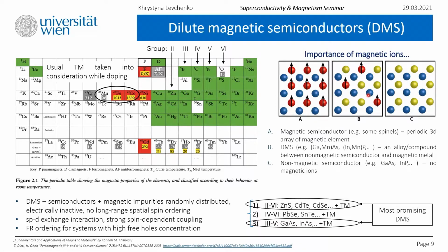The most characteristic feature of the DMS is a giant spin splitting, which increases the spin polarization of carriers, and increasing the carrier concentration. Increasing the concentration of the transition metal ions may lead, at least in the case of gallium manganese arsenide, to the appearance of a ferromagnetic phase.